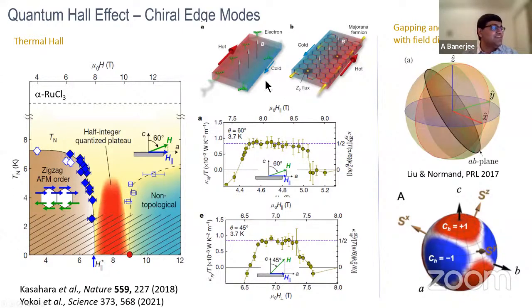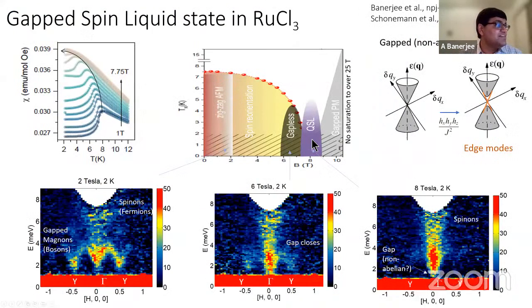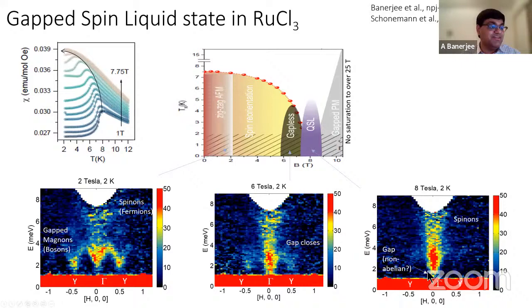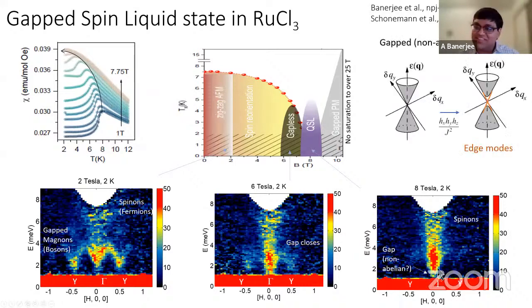So what they did was they actually attached thermometers on a piece of sample in the Hall configuration, and they used a kind of measurement called the Righi-Leduc measurement. It's a very difficult measurement, by the way, especially in a high field. But when you do that, the Hall conductivity basically has a half-quantized plateau, which corresponds to a value of half here. And this is a robust state that they saw, exactly where we saw this quantum spin liquid ground state with this gap, probably this gap state right here.